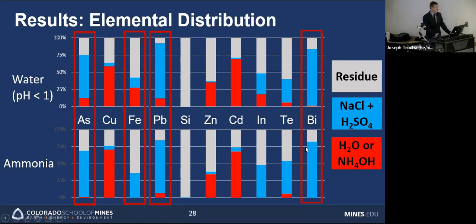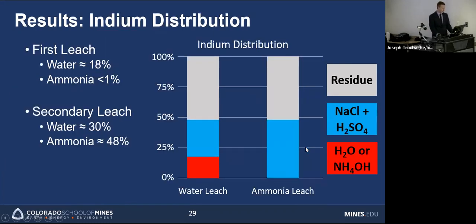Next, here are a number of deleterious and then just burdensome metals included. Arsenic, lead, and then bismuth all had higher recoveries in water leaching as opposed to ammoniacal leaching. Bismuth was ever so slight, so the process improvement has to be weighed on economic benefits. Another thing I'll mention is that iron, while not deleterious, just results in extra material having to be processed.